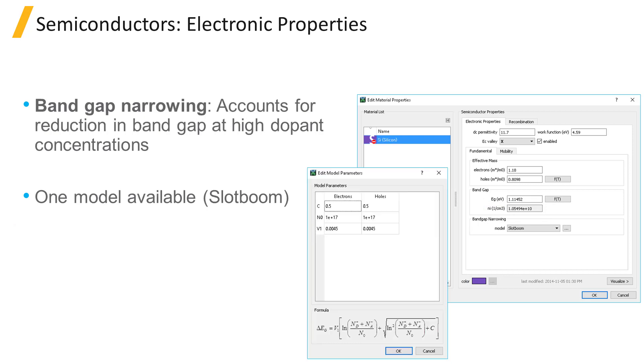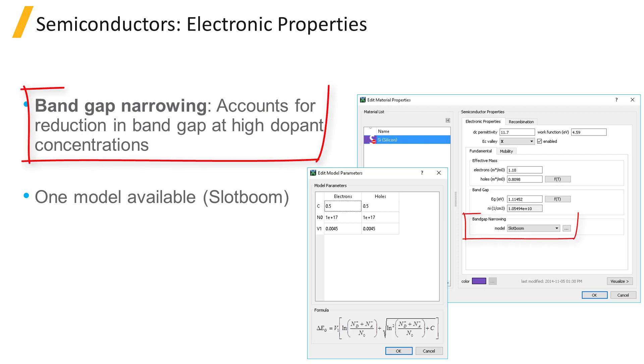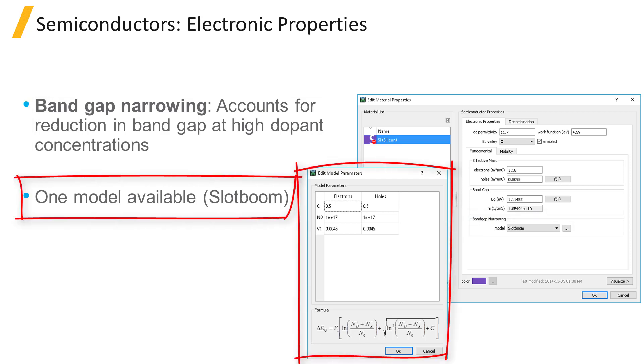When impurities are added to the intrinsic or pure semiconductor, localized allowed energy states may be introduced at energies that lie within the bandgap. In the case of dopants, these impurity states will exist with energies near the conduction or valence band edges, such that the dopants readily ionize at moderate temperatures. When the concentration of dopants is large, these discrete states will begin to merge and form a thin band of allowed states within the bandgap, effectively narrowing the bandgap. This can be viewed as a narrowing of the bandgap or an increase in the effective density of states. The Slotboom model for bandgap narrowing is provided in device to account for this effect.